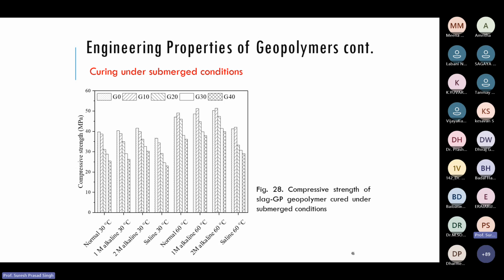So if you have a geopolymer sample and put it in normal water for curing, there will be a reduction in strength. Instead of this, if you have alkaline water, the same thing, the strength reduction will not be there. And as the temperature increases, the strength also increases.